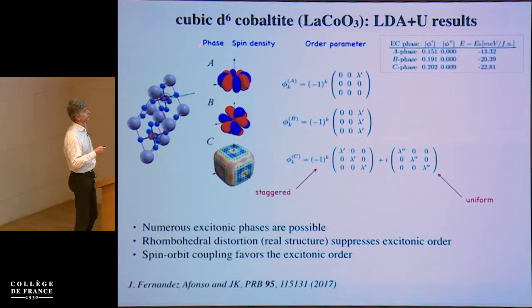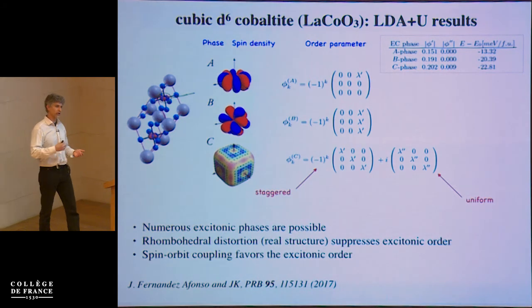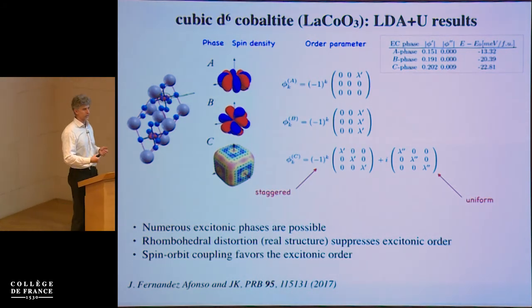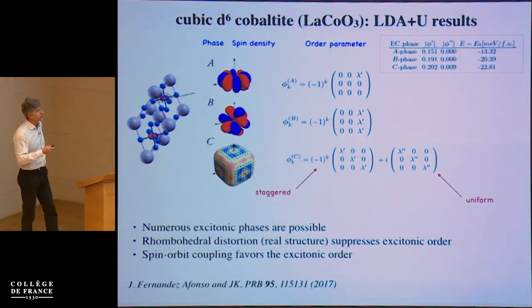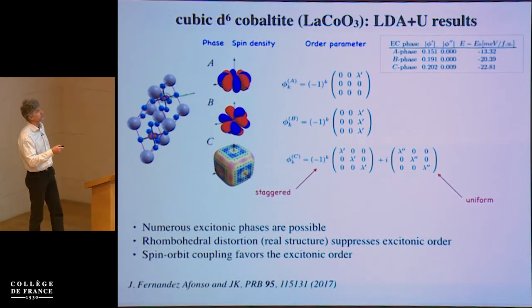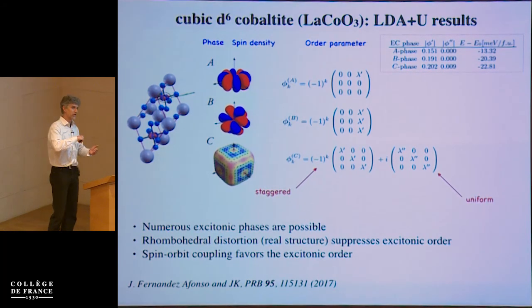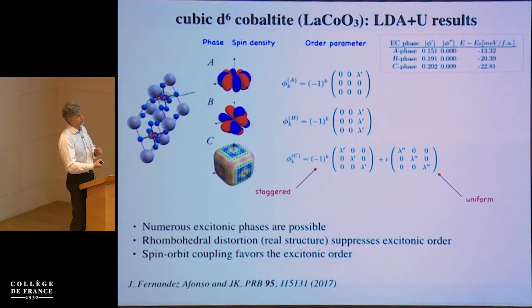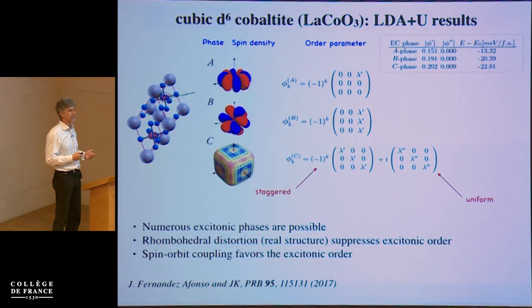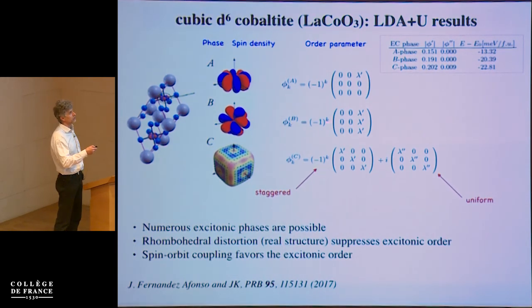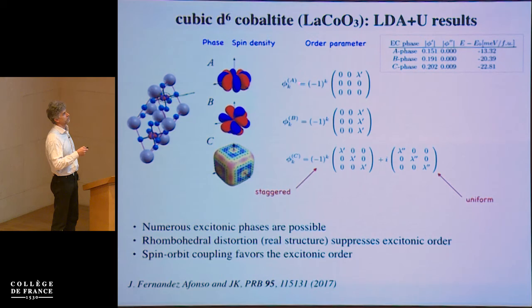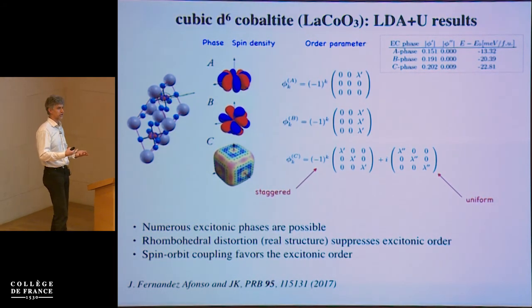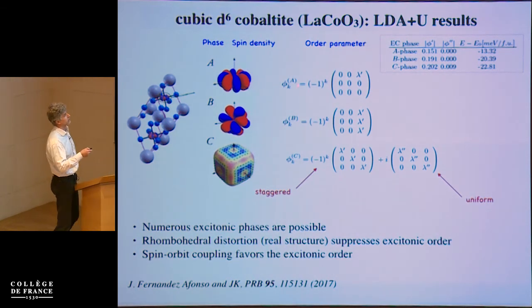Just to go quickly through this, if we go to real materials, the physics gets much richer, because we have not only a spin degree of freedom, but our excitons also can have some orbital degrees of freedom. So in D6 perovskites, we would have 3 orbital degrees of freedom and 3 spin degrees of freedom, so in total 9 excitons, allowing us to build many different excitonic phases described by an order parameter which is actually a second rank tensor.